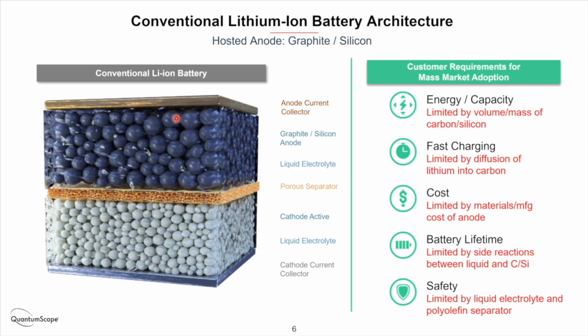And second, because you could actually form dendrites where lithium would grow in these mossy or dendritic structures, penetrate through the separator and bridge to the cathode, at which point the battery fails. So the anode is also responsible for some of the fast charge limitations. In terms of cost, well, it costs money to buy the active materials and to deposit them.